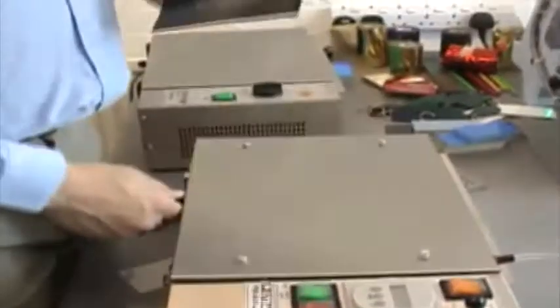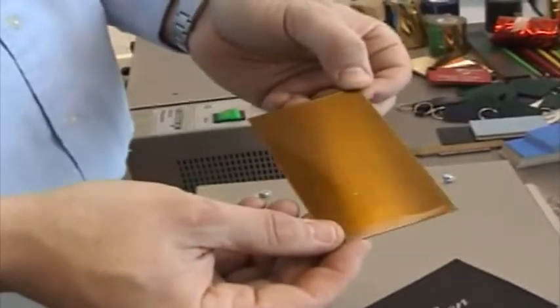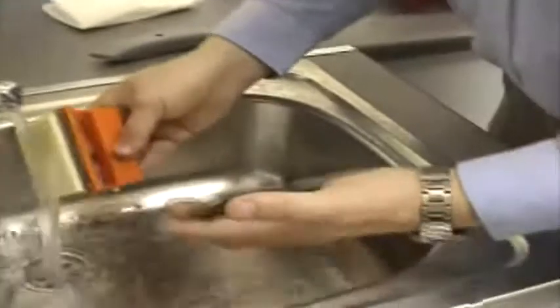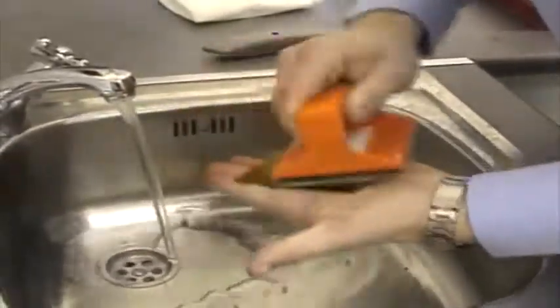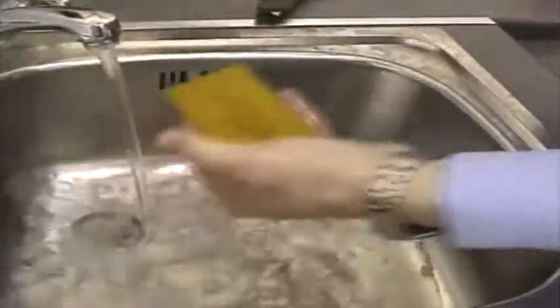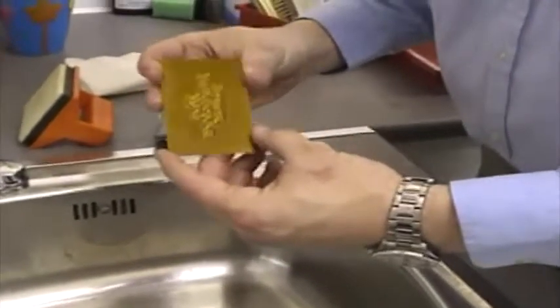It's always a good sign when the negative is stuck to the polymer plate. If we peel that off, there is an image there, but it's not in relief — this design has been superimposed on here. Now what we need to do is wash the plate to wash away the excess, leaving our design with the plate. To do that, we need to use water and a sink. Wet your polymer plate and your washout pad. Hold the polymer plate in the flat of your hand and very gently let the bristles of the pad do the work — don't force it down. Just go round and round in circles, nice and gently. Keep dipping it under the water, and very gradually you'll see the image almost magically lift itself from the polymer plate. And there we have one polymer plate. The washing should take no more than two or three minutes — the danger is over-washing the plate.